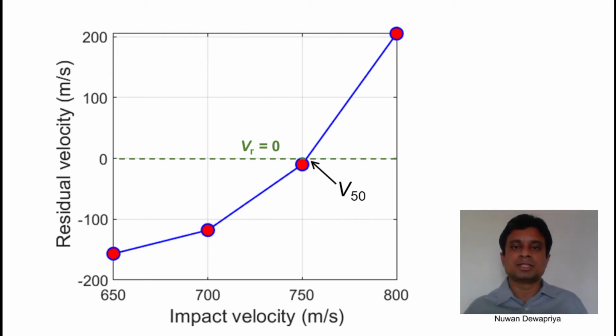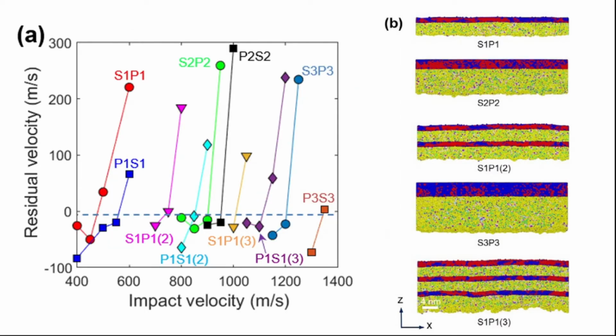Now we can plot the impact velocity versus residual velocity. When the impact velocity is 650 meters per second, the projectile bounces back, so the residual velocity is negative. When the impact velocity is 800 meters per second, the projectile completely penetrates the target, so the residual velocity is positive. We define the impact velocity when the residual velocity is 0 as the V50 of the target. We repeated the same exercise for all 10 targets and computed V50s.